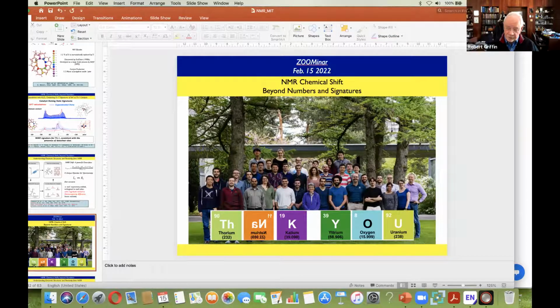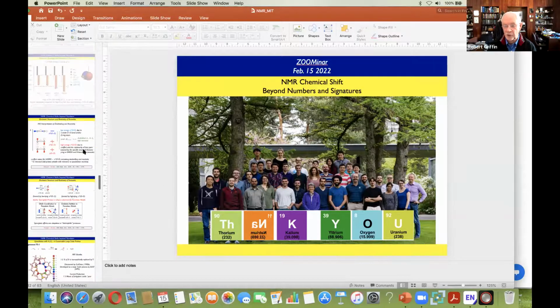One of the things that you've seen that's somewhat different than what we've seen initially in shift anisotropies is that, for example, it used to be that in at least carbon compounds, carbonyls, the sigma 1,1 and 3,3 elements would stay put, and what you would see would be a movement of sigma 2,2. Now you're seeing sigma 1,1 really going up and down quite a lot. So what's involved when you have sigma 2,2 only moving?